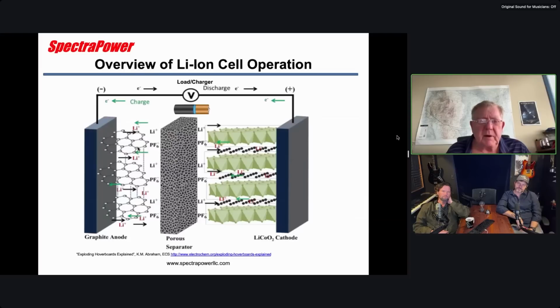One of the biggest safety problems you can run into is if you try and charge too quickly, you can plate lithium metal onto the surface of the anode. And it's actually a pretty common problem. We take apart lots of cells, and it's not unusual to see lithium metal plated in spots. Because if you think about the electrodes, they're not perfect. There's some spots higher, some are lower. If you have a thin spot on your electrode, there may not be enough room for the lithium to get in, so it just ends up plating onto the surface and forming lithium metal. You can see it because it's a silver looking material. That's one thing you have to watch out for.